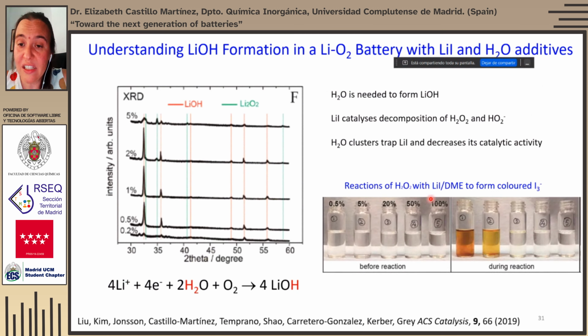This can be further seen in these photographs where different amounts of water were added to a solution of hydrogen peroxide, and some lithium iodide and DME were added. And when the amount of water was adequate, there was oxidation from the iodide to the triiodide, and therefore the solutions were colored. Still, even if this chemistry seems very promising, there are still some issues to solve. For example, this battery actually works with oxygen, not with air, and it is necessary to take into account that you need to avoid CO2, you need to avoid some other atmospheric pollutants, as well as avoid this redox mediator travelling from the cathode to the lithium metal.